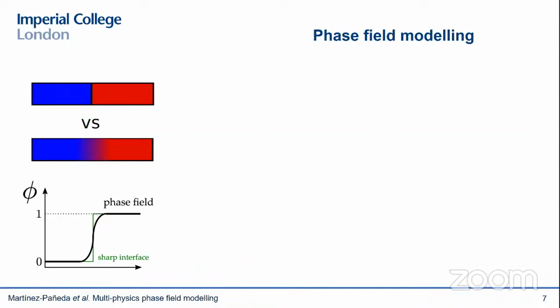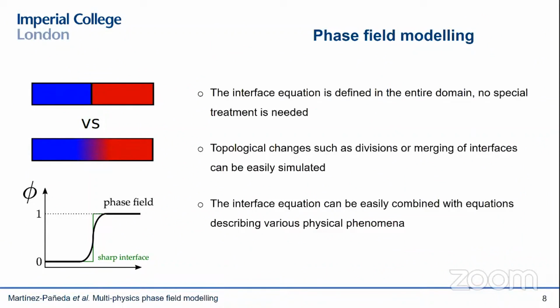So this could be cracks propagating, this could be grain boundaries evolving, whatever interfacial problem that you have, this very simple computational idea is quite powerful, and it allows you to track interfaces easily. And there's three key advantages that I always like to emphasize. The first one is that the interface equation is defined in the entire domain, so there's no need for any special treatment. The second one is that topological changes such as merging or divisions of interfaces can be naturally captured without any ad hoc criteria. And the final one is that it's very well suited for multi-physics problems, because you can easily couple that interface equation with equations describing other physical phenomena. So this is something that we're going to use quite significantly.